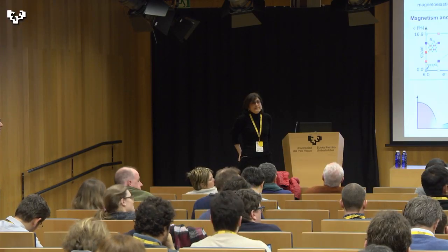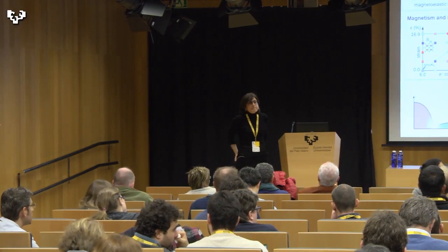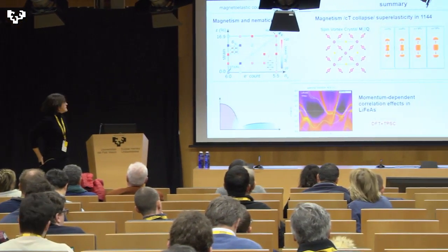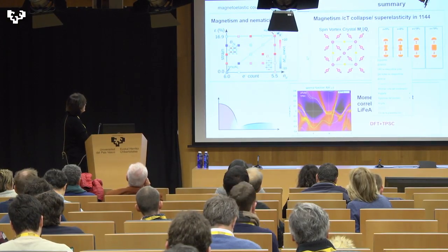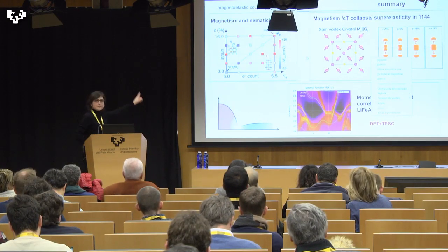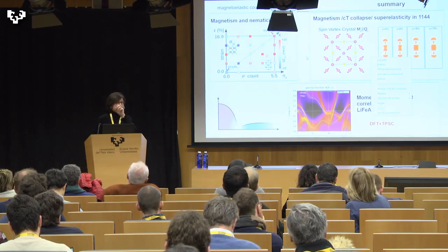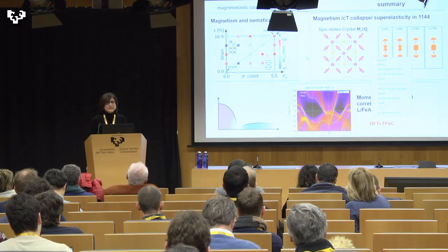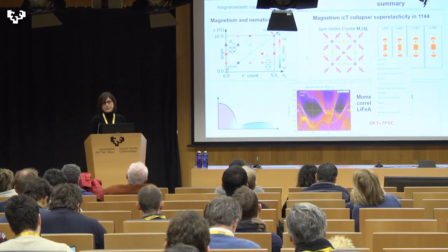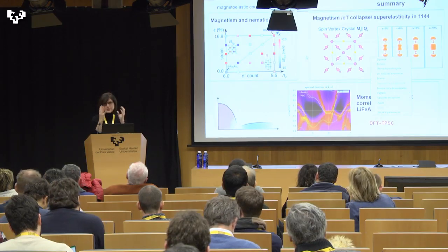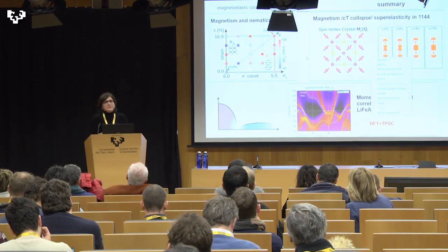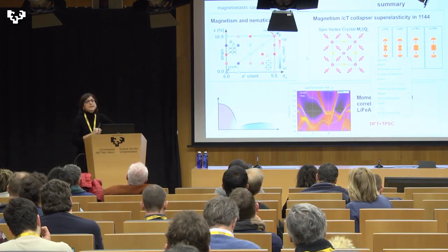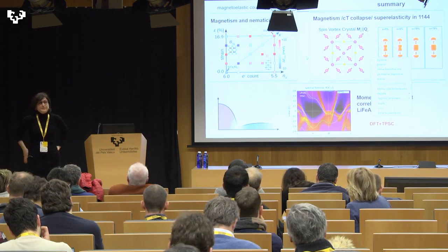I was wondering if spin orbit is included in the calculation, and if it's relevant, if it can change things. Spin-orbit is relevant here, definitely, in the spin vortex state. Here you have to work with spin-orbit coupling, and it's important. In fact, spin-orbit coupling is important in these materials, especially, as we know, in the regions where you have band crossings, and we have to investigate that, but spin-orbit is important, even though it's a 3D system. For this kind of states, you do have spin-orbit. Yeah. Thanks.